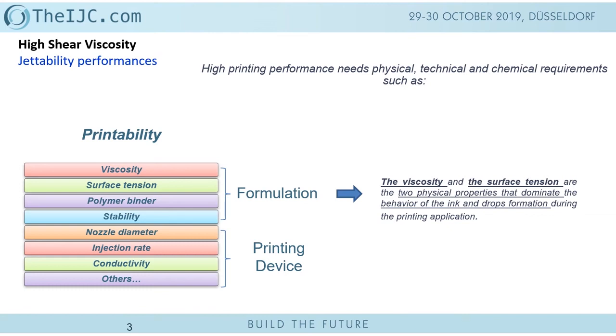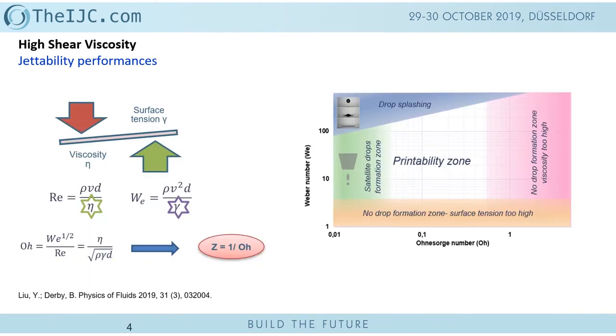In terms of formulation there is a balance to achieve in terms of surface tension and viscosity. There are limits for high viscosity values and low surface tension values. In literature we find this dimensionless diagram in terms of the Weber number and Ohnesorge number that describes zones considering the physical properties of the ink and what issues we may encounter. It's theoretical, but it gives an insight into the behavior of the ink during printing, including the printability zone and issues such as drop satellite formation.